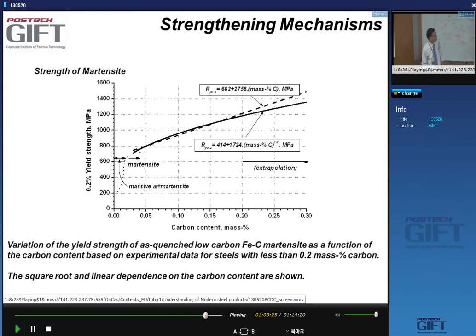And you can see that over a range that's technically very important, from about 0.02% to about 0.2% here, these two functions are basically the same. You can't tell them apart. So carbon is the most important parameter. You see here that as the carbon content decreases, martensite becomes very soft. Yes?